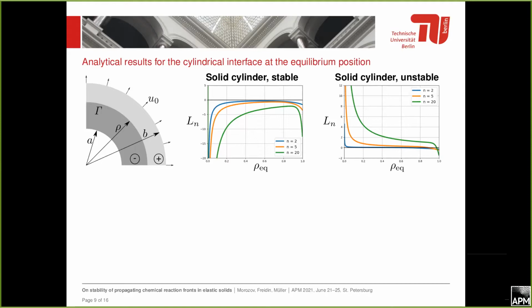What is shown in these plots is that we adjust our external load to put our equilibrium position at various radii. So it means that, for example, on the left slide, we consider a solid cylinder, and a certain load was applied to have our equilibrium position at 0.6, for example. And that means for wave numbers 2, 5, and 20, we see only negative values for Ln, and we consider this configuration stable. We cannot prove that all of them will go down, but we see the tendency that very high wave numbers are even lower.